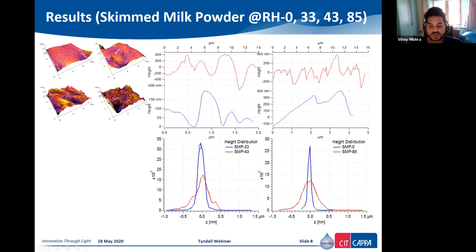Now, I also tried to show the height distribution on the surface of skim milk powder just before the lactose crystallization has started and at the moment when lactose crystallization happened. Now, the blue curve here represents the skim milk powder at relative humidity 33, while the red curve shows a broader peak or distribution of peaks on the surface. You can see there were fewer peaks on the surface. That's why we have a narrow distribution of height, while we have a broader distribution